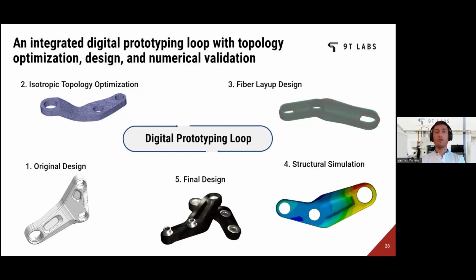However, isotropic topology optimization already gives us a really great framework, a skeleton, where we can then in step number 3, when we use our Fibrify design software, place the material along the load path. So that's really the goal out of this topology optimization, is to understand where are the core load paths and then place the continuous fiber really exactly where those maximum loads are. And of course, where we don't need the continuous fibers, then it's about thinking what is the best possible way to get to the final geometry with different other sets of materials. Could be the neat filament from the printer or the chopped fiber filament, but could also be overmolding or adding an organosheet. In this case, we will see that it's about adding an organosheet.